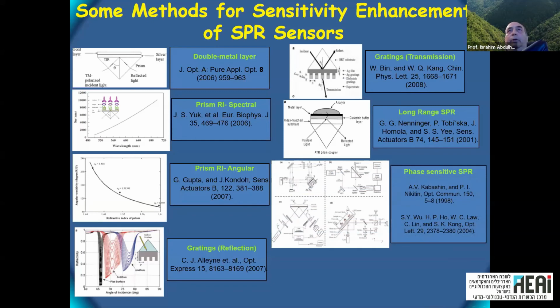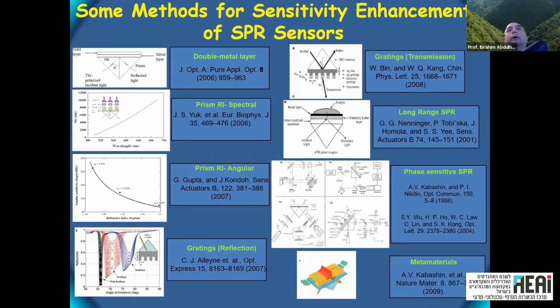And of course, there are other ways of doing it, like what's called phase-sensitive SPR, because the phase curve is sharper than the intensity curve, then you might be able to get a better detection limit. I will try to explain it later. This shows a metamaterial type structure, mainly columnar type structure, and shows higher sensitivity. It is more like playing with the metal properties, because it becomes like a composite metal with certain properties. You think about it like a metal with a lot of dielectric in between, so it is less absorbing. And that's why it becomes better, actually.